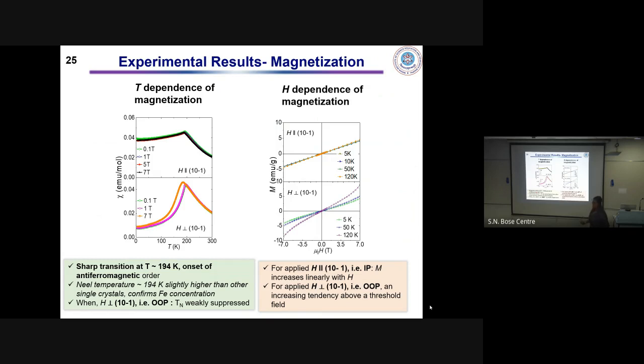Yes. So we think that might be because of the spin flop. But I think spin flop will be directly seen more in magnetization data than in transport data. But this behavior is also an indication of the spin flop, right? After 120 Kelvin, when we measure the curves, all the curves show the tendency of increment after a certain magnetic field. So the transition is very sudden. Basically, with spin flop you see some sudden transition, not any continuous change.